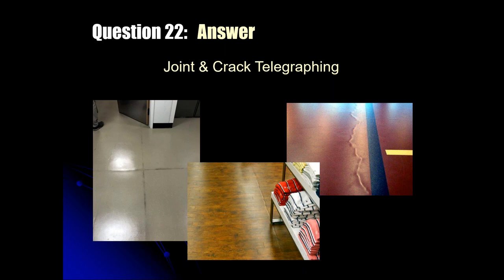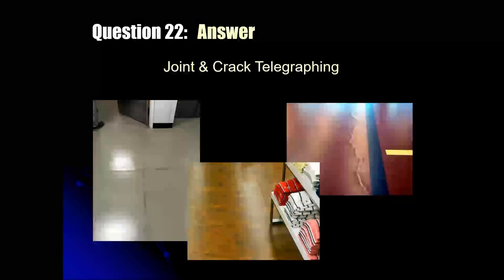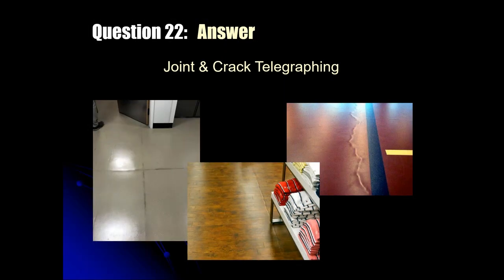In all cases, the slab sections at the joints or cracks may have had even a small measure of curl or upward warping. The flooring installer may have ground it nice and level, may have floated up to it or over it and leveled it out, smoothed it out, forgetting that when a slab curls or warps upward, it's lost contact with the base. Whether that base is the vapor retarder, the ground, or the metal decking, there's a void.